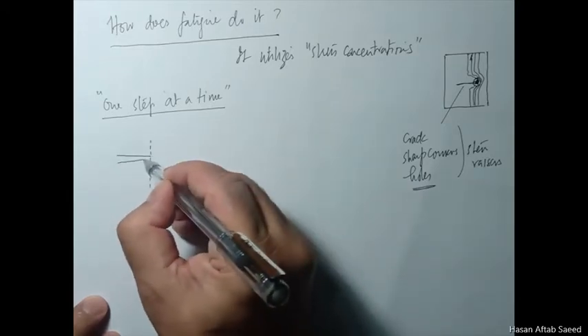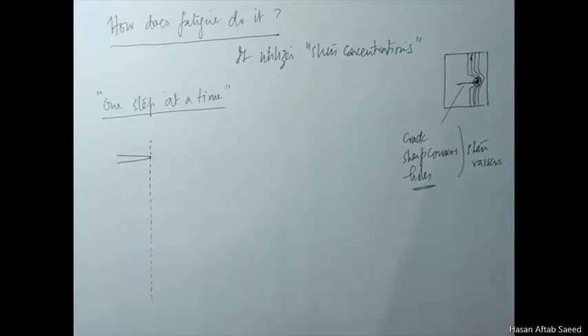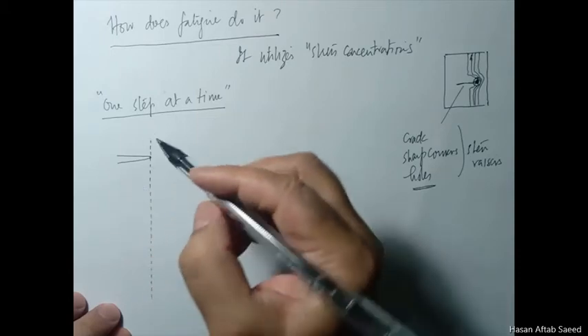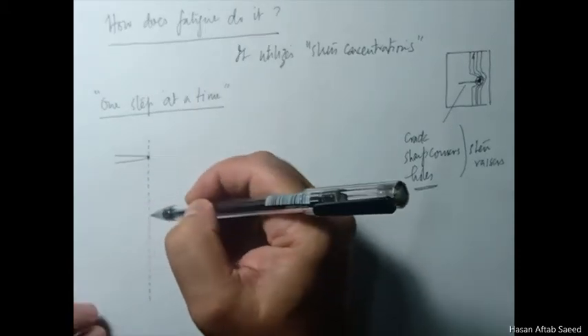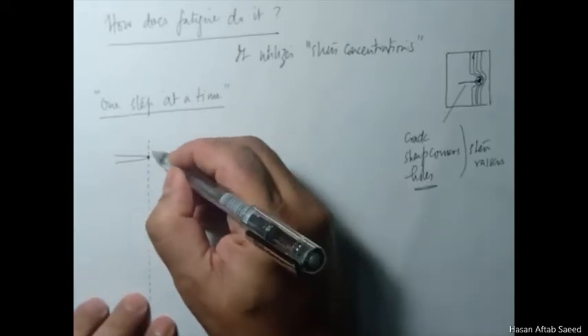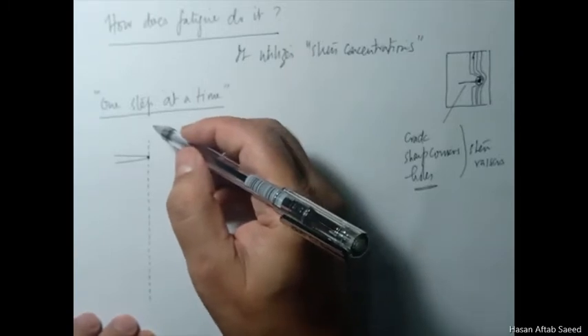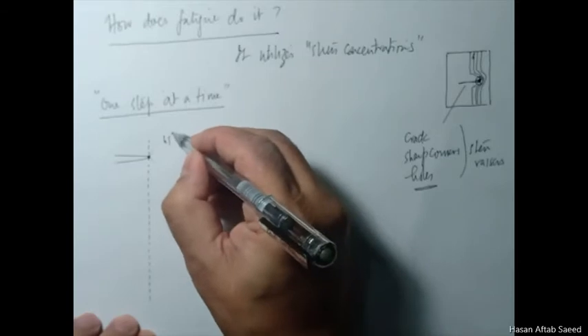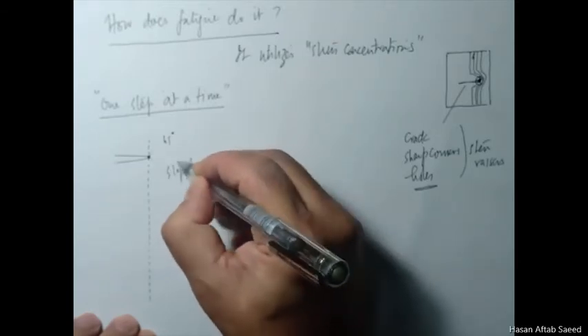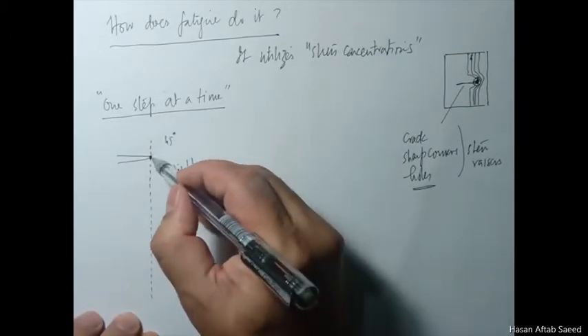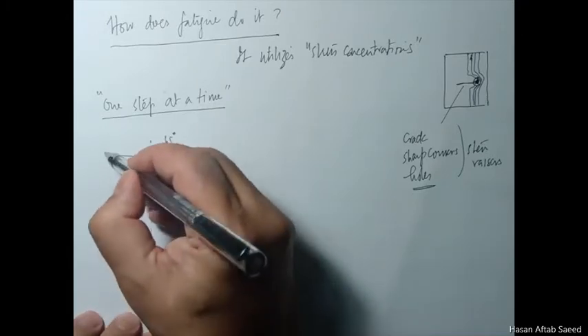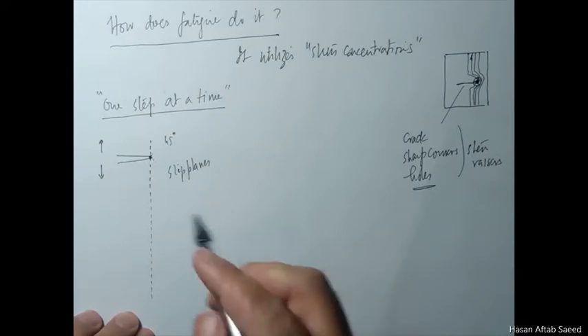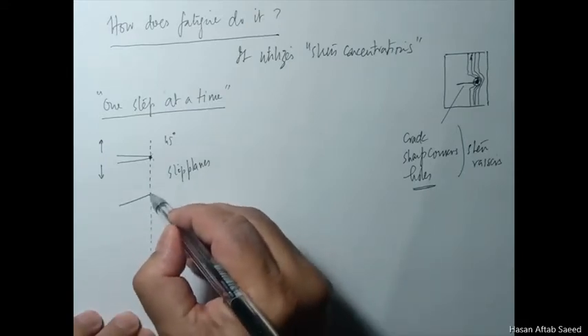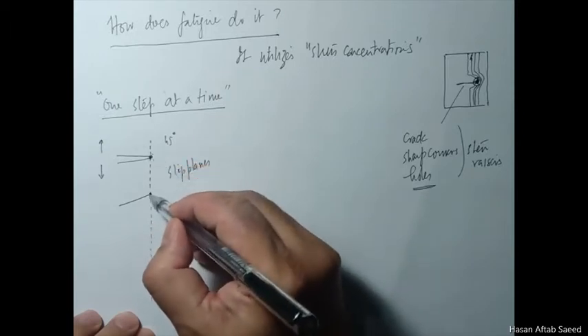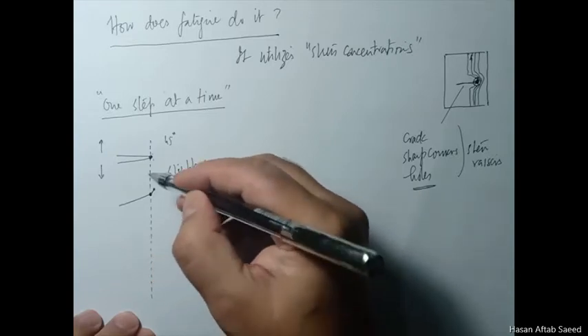Here a crack is there, and just assume that the crack is there already. We'll discuss how and why a crack should be there. Crack is here, and this is the point where there is a very high stress concentration, and the material is ductile material. We are only dealing with ductile materials, tough materials. So at 45 degrees you have slip planes, and there are a number of slip planes, complementary planes. Now at this point, when you apply the tensile loading, what happens is that there is an atomic slip that occurs on the slip plane.